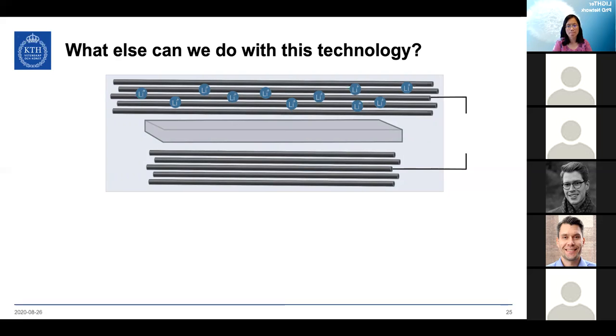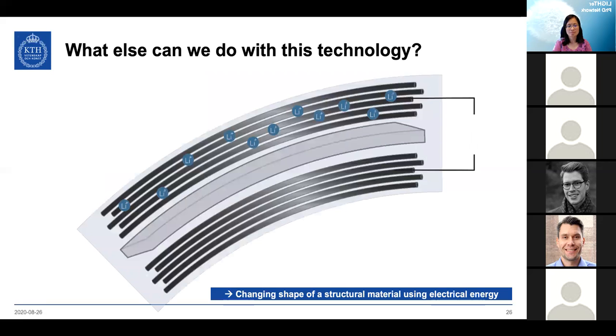This means that one layer gets filled with lithium ions and the other gets emptied. What happens then is that the carbon fibers in the layer that gets filled expand, while the carbon fibers in the one that gets emptied contract. However, the real case does not really look like this. It looks like this. The expansion and contraction of the carbon fiber layers leads to a bending motion of the stiff and structural carbon fiber material.